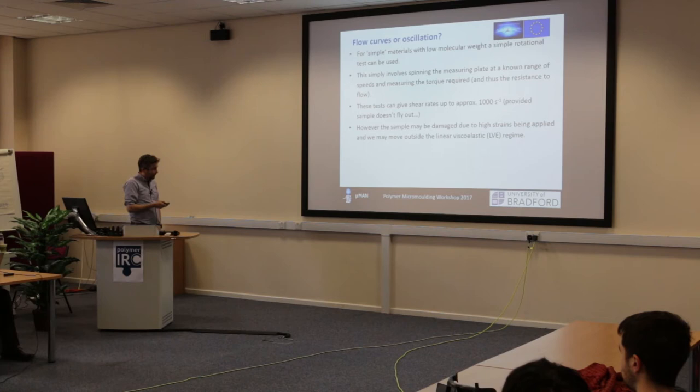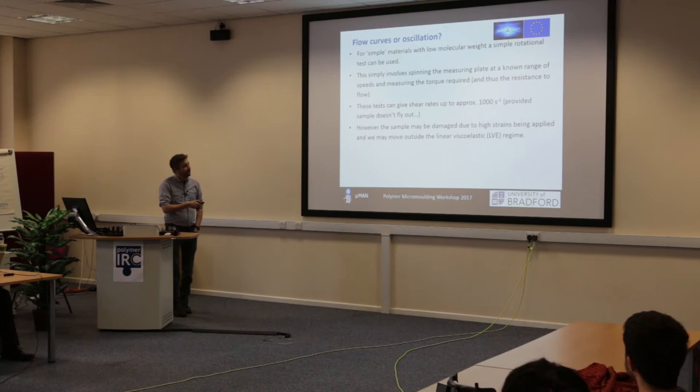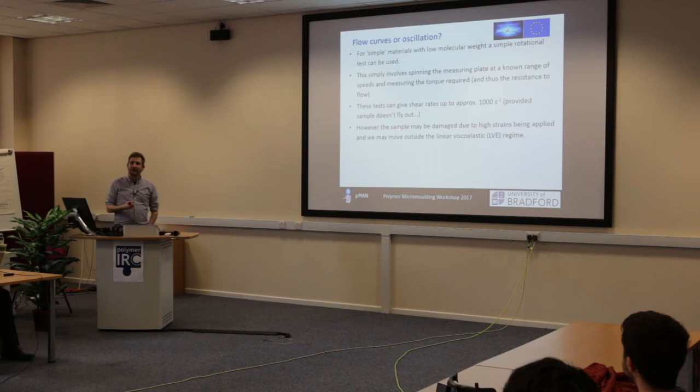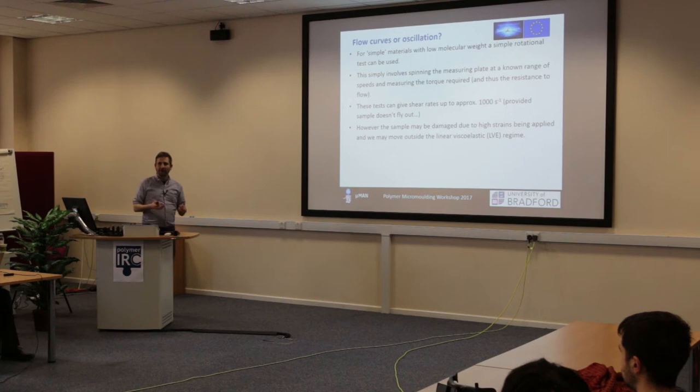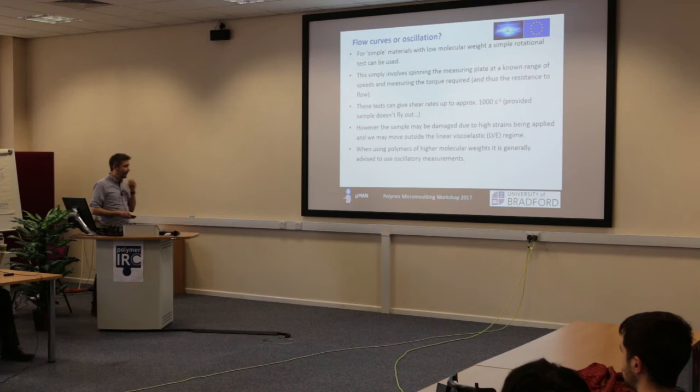As I say, if you apply these high strains, then we move outside this linear viscoelastic regime, okay? And when we move outside that, we don't really know the rules, okay? There are rules being developed, constitutive equations being developed all the time for understanding viscous behavior in this way, but they are hideously complex, and they all involve everything that we're trying to measure you need to know prior to actually putting them into the viscoelastic tool, okay? So what we try and do is remain within this LVE, okay? And in order to do that, we have to do a couple of different tests.